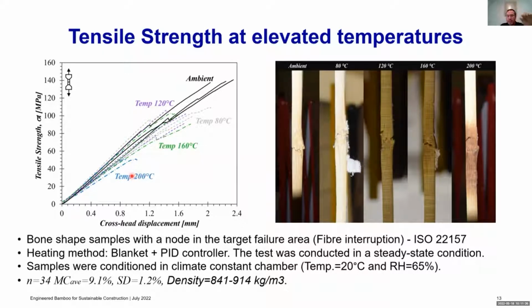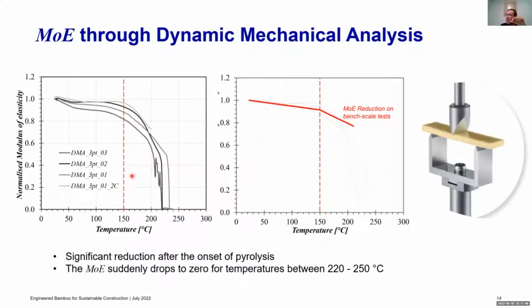We did tests at a smaller scale, what is called DMA test, which is a very small scale bending test to avoid heat transfer issues because of the size of the samples. And with the DMA, what you do is that you measure the reduction in the modulus of elasticity. So what you see here is a normalized modulus of elasticity against temperature again. And you see that there is a decrease in the modulus of elasticity, but after 150 degrees, the slope of that curve drastically changes, and then you see a significant drop in the modulus of elasticity, where after 230, 240 degrees, the stiffness was completely gone.